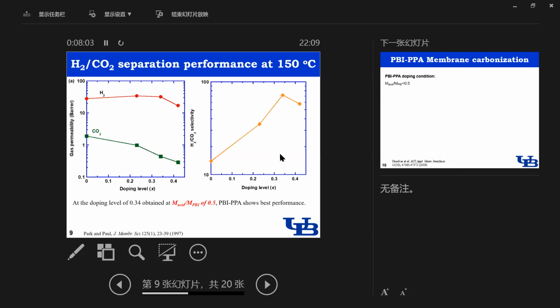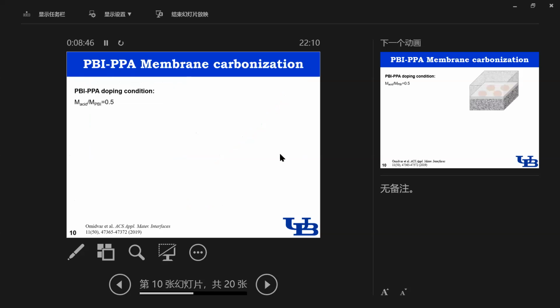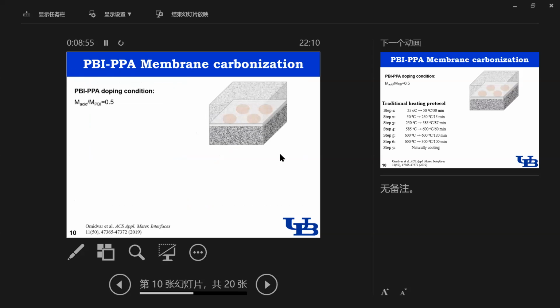Then we tested pure gas hydrogen CO2 separation performance at 150 degrees C. Firstly, for hydrogen, the permeability has little change until the high doping level at 0.42. For CO2, its permeability decreased with the doping level, and this causes hydrogen CO2 selectivity to increase first and then decrease. At the doping level of 0.34, obtained at the acid PBI molar ratio of 0.5, we get the best hydrogen CO2 separation performance, and then we use this doping condition to produce CMS membranes. So first, we sandwich those acid doped PBIs in ceramic plates and go through the carbonization procedures.